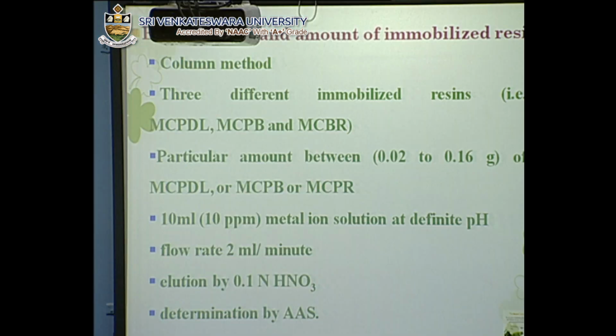The effect of type and the amount of immobilized resins. For this, we have used the column method, 3 different immobilized resins, that is Calotropis procera bark, root and dry latex. The amount of the resin was from 0.02 to 0.16 gram of modified resins. Flow rate was 2 ml per minute, and elution was carried out by 0.1 normal HNO3.